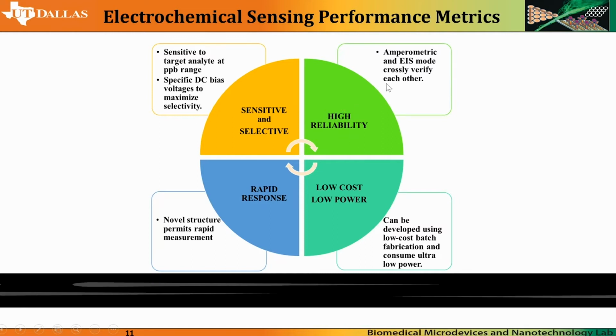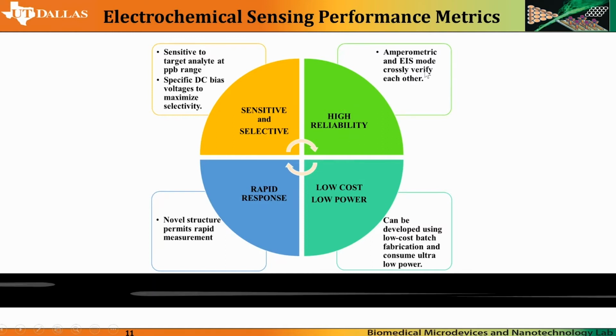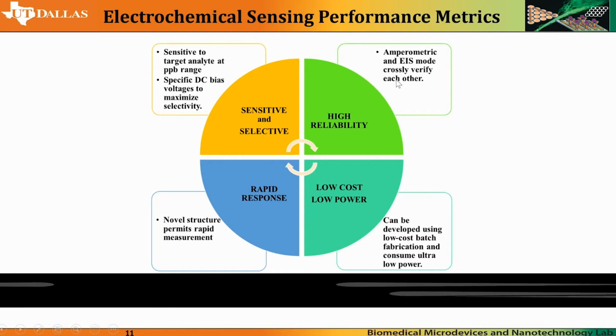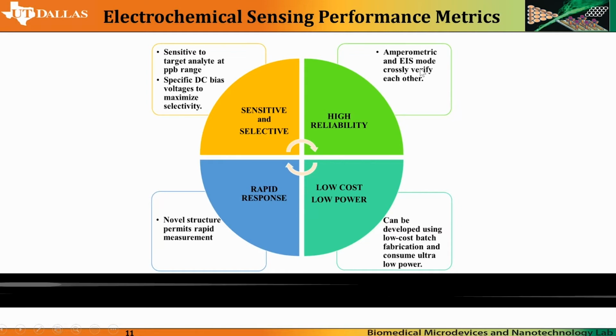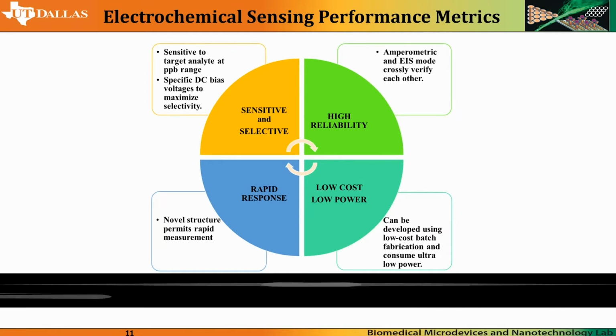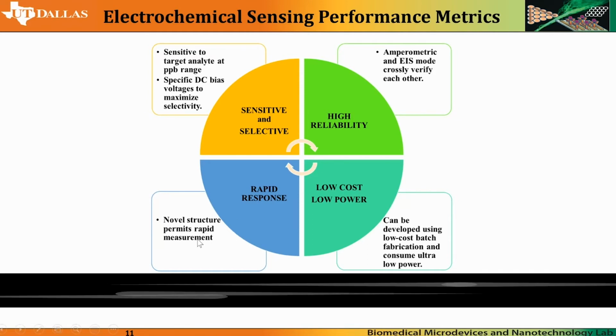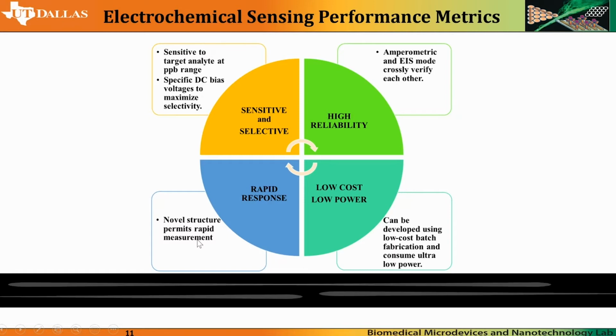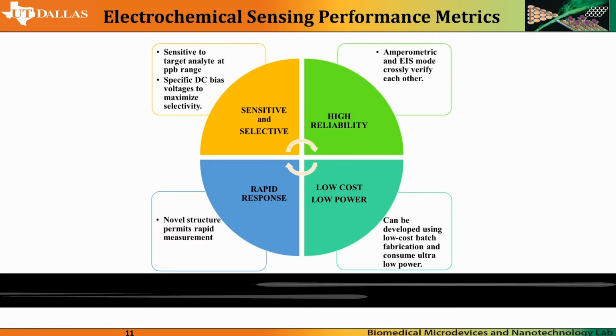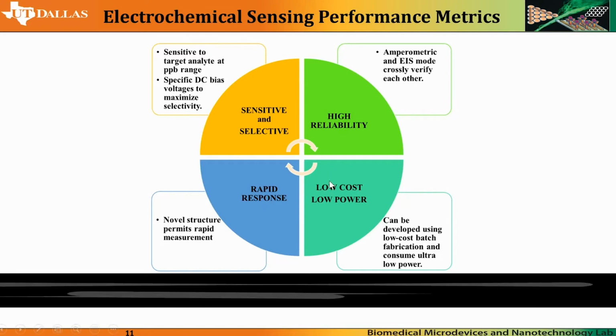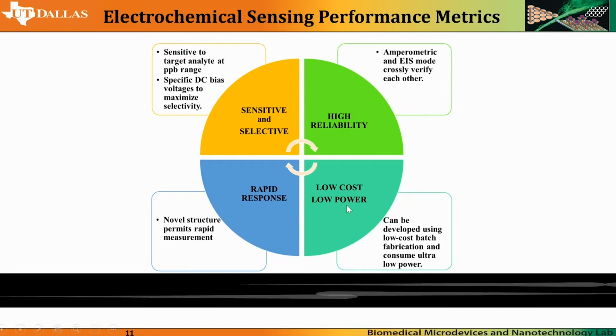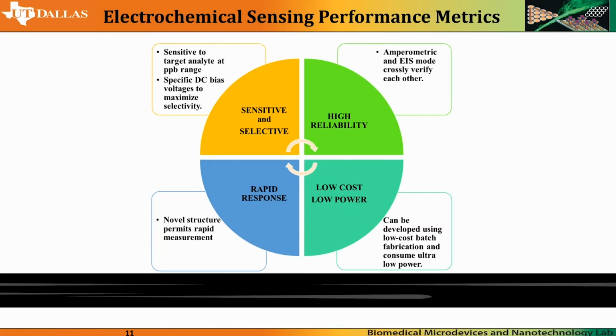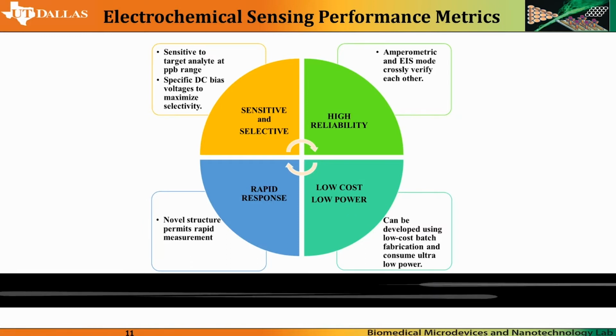High reliability: we'll be using dual techniques to verify the results obtained. In our case, we'll be using amperometry and EIS to cross-validate the results. Rapid response: since it is a novel structure that we'll be using, it permits rapid measurements such that the current can be detected at 5 seconds. Low cost and low power: the sensing device can be developed using low-cost batch fabrication, and it uses ultra-low power microprocessors.